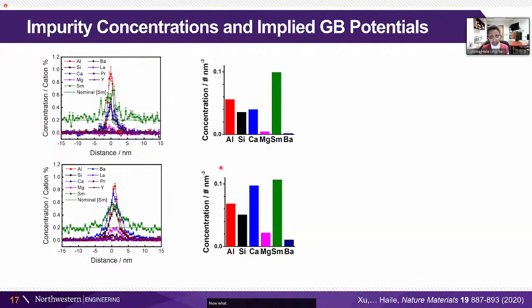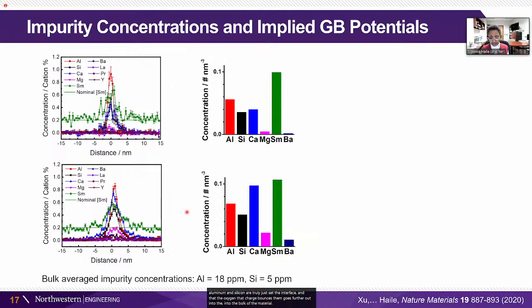Now, what we've done is say, let's imagine then that the aluminum and silicon are truly just at the interface, and that the oxygen that charge balances them goes further out into the bulk of the material. And from that, we can analyze the behavior. And let me just say that the overall bulk average impurity concentrations here are 18 and 5 parts per million of aluminum and silicon respectively.